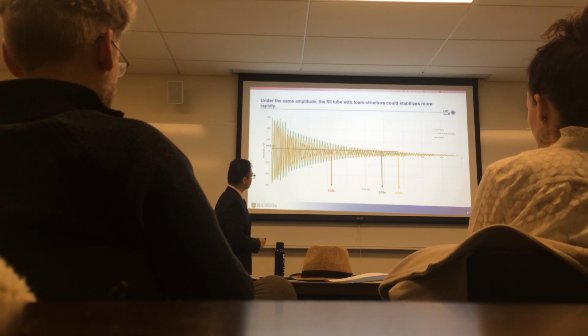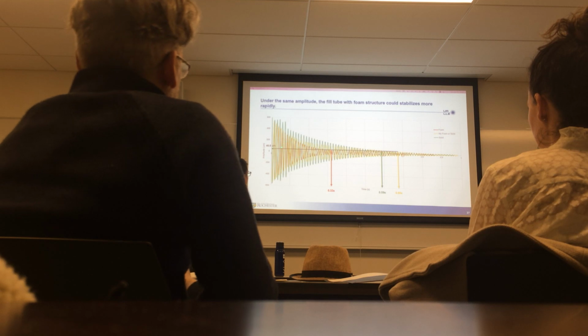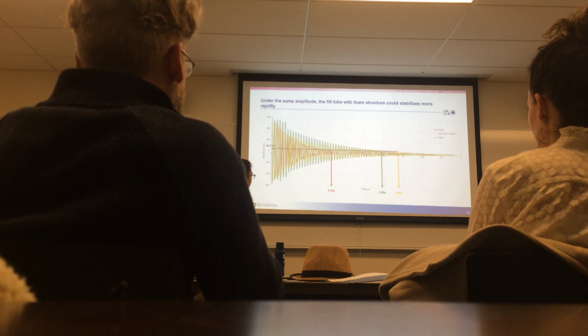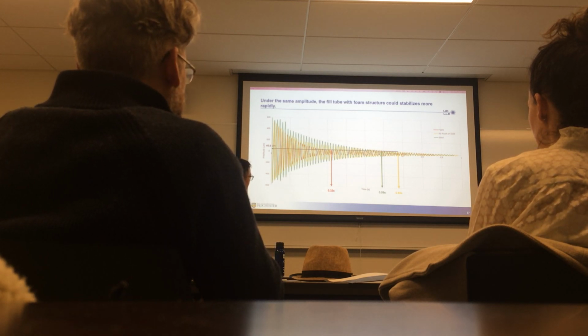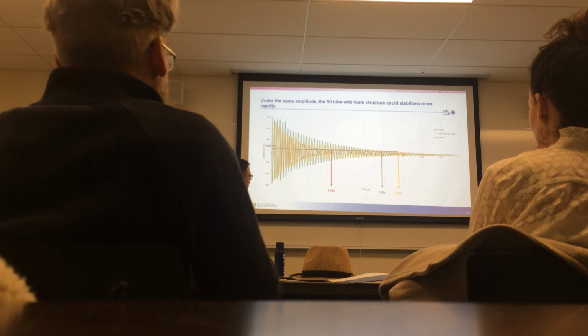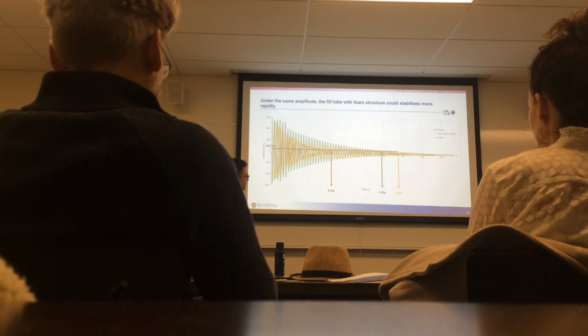At first, we compare the decay time. When the target decays to 40 micrometers, that is 94% of the total displacement. The fill tube with the foam structure uses just 0.3 seconds, and the fill tube without the foam structure still uses 0.6 to 0.7 seconds. That's a 50% decrease. That's a very good result.